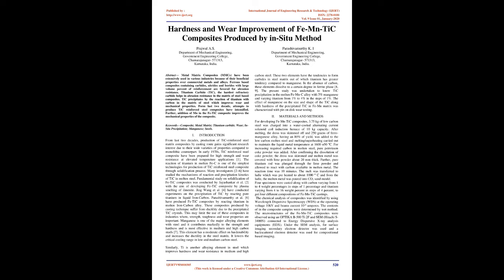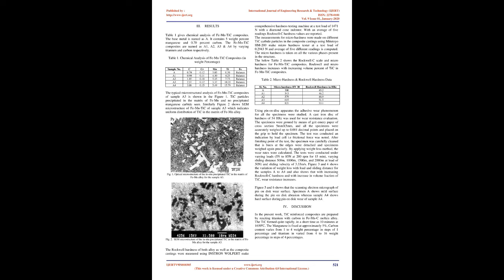After melting, the dross was skimmed off and 250 grams of ferromanganese alloy, having an 80% yield, was added to the low-carbon molten steel, and melting/superheating was carried out to maintain the liquid metal temperature at 1600 plus or minus 50 degrees C. For increasing required carbon in molten steel, pure petroleum coke powder was added. After confirming the dissolution of coke powder, the dross was skimmed and molten metal was covered with lime powder about 20 mm thick. Further, pure titanium rod was plunged through the lime powder and allowed to react with carbon available in molten metal. The reaction time was 10 minutes.